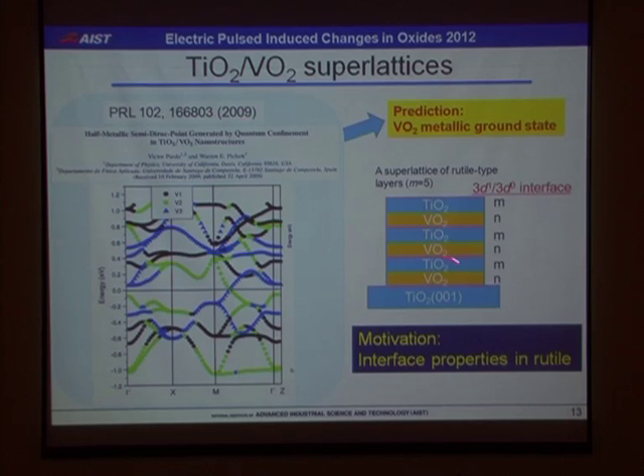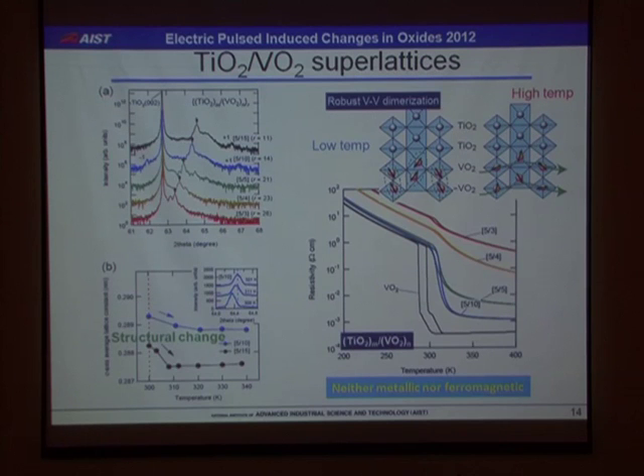So we constructed this kind of superlattice structure, and actually the similar d1, d0 system has been intensively studied in the perovskite structure, but less in other systems. So another motivation is to investigate interface properties in the rutile structure. This is the XRD pattern, and here the layer thickness of TiO2 is fixed at 5 unit cells, and that of VO2 is varied. And here is the temperature dependence of the lattice constant. As you can see, there is a sharp decrease around 300 or 310 Kelvin.